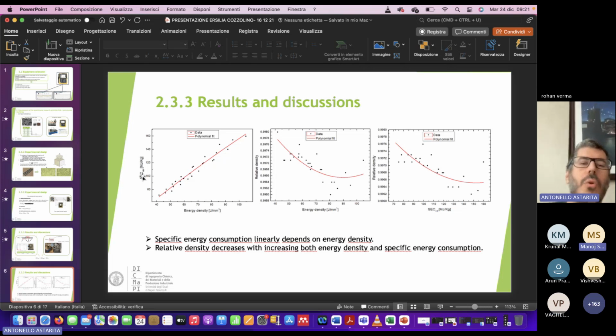Okay. So as you can see, by increasing the energy density, you also increase the specific energy consumption. We have a kind of linear fit between these two entities. So the first immediate result is that you should try to reduce energy density in 3D printing to reduce the energy consumption. Another interesting link is the link between the density of the printed parts and the energy density adopted,